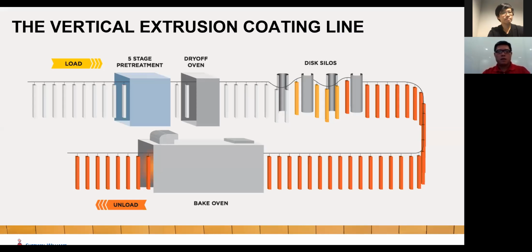And you can see this line, okay? This is an extrusion coating line. So the parts are loaded to the pre-treatment section as well. It basically goes through the whole process again, but it's hanging on the parts. They go through the pre-treatment, then spray 3 layers of coating, wet on wet mainly, and then go through the oven. When it comes out of the oven, it becomes 100% cured. Then we can take it off the shelf and ship to the construction site. So that's the whole process.